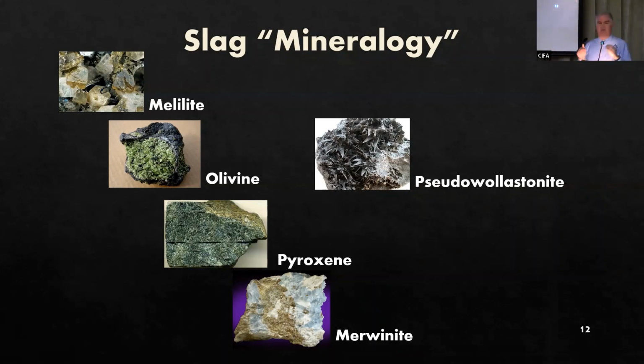The formation of the crystals of these minerals is a function of the composition of the slag and also how rapidly the slag cools once it's removed from the furnace. It starts to crystallize. If the slag cools quickly, which it most often does, then there's not enough time for the crystals to form, and so you get very glassy slags. We were talking about that a little bit before the talk started tonight. Glass is non-crystalline, and so it's what's called amorphous.